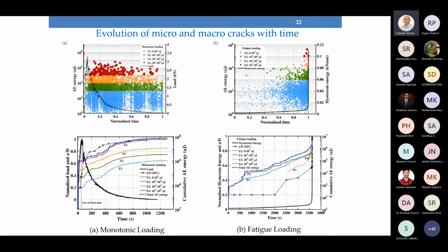See, initially up to 50% of the fatigue life, it's horizontal, meaning there is no crack growth. We don't see any crack in the digital images, but after 50% of the life, we see an increase in the crack growth on the surface, and then finally this becomes vertical, meaning a sudden crack growth takes place, leading to failure. So from acoustic emission and digital imaging, these two techniques complement each other, and we are able to obtain the complete mechanisms of crack growth, their coalescence, and formation of a macro crack.